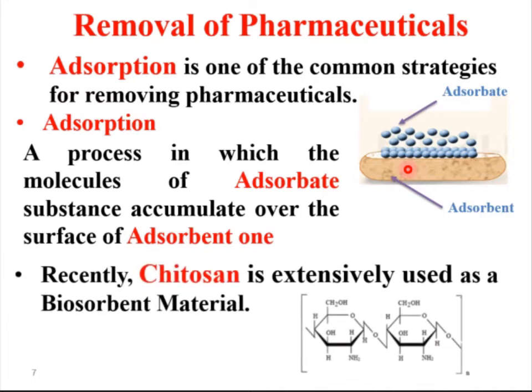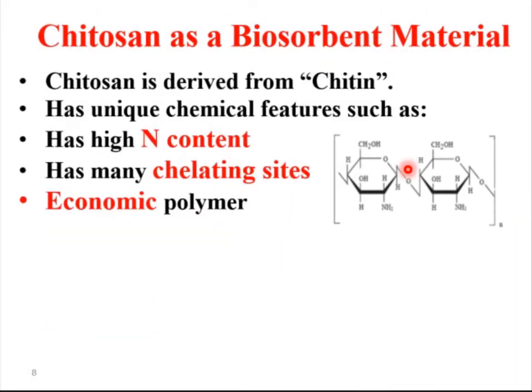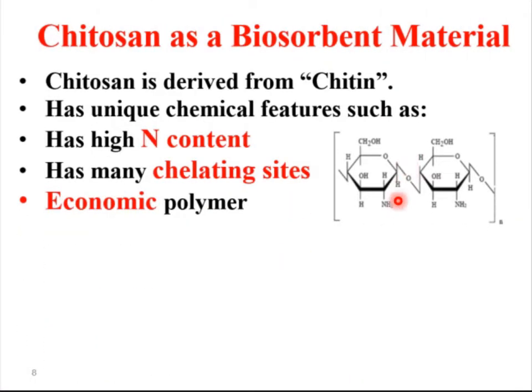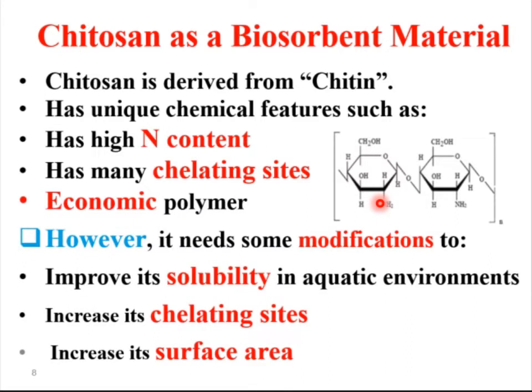Recently, chitosan is extensively used as a biosorbent material for its unique chemical features, such as its high N content, unlike other biopolymers. It has many chelating sites like hydroxyl groups and amine groups, and also it is an economic polymer. However, chitosan to be used as a biosorbent material needs some modifications regarding its solubility in aquatic environment, its chelating sites, and increasing its specific surface area.